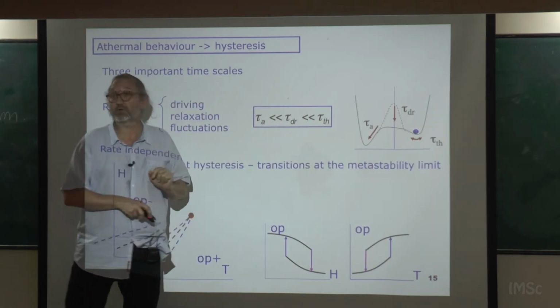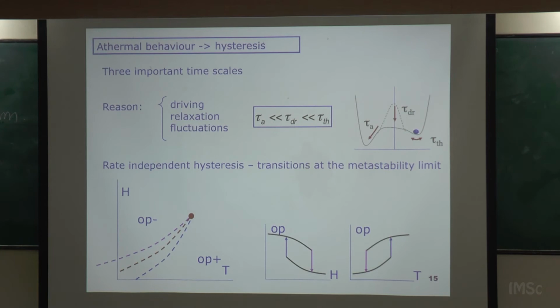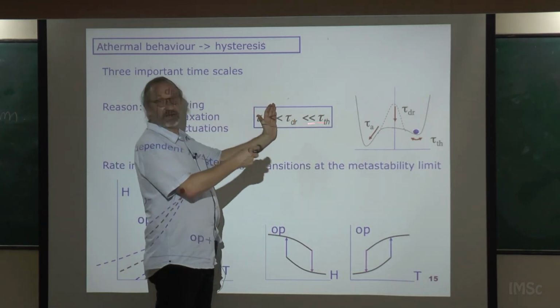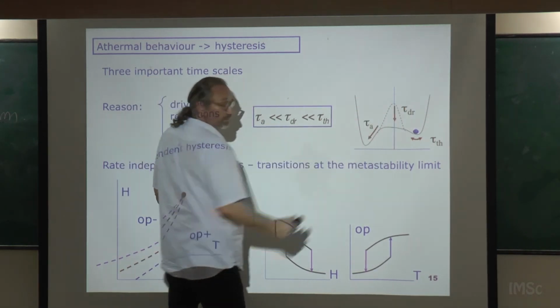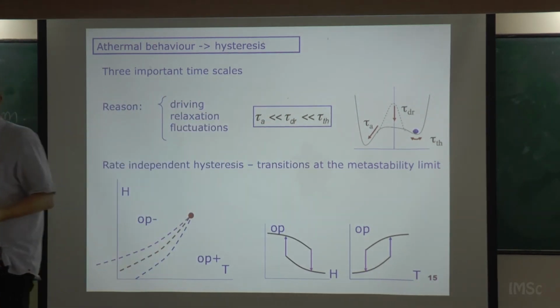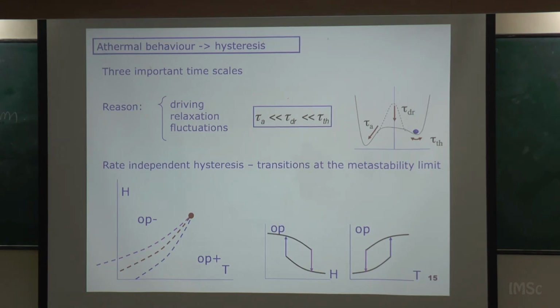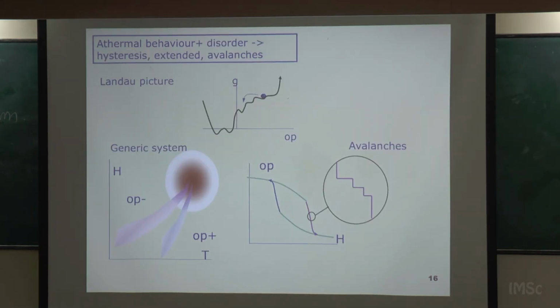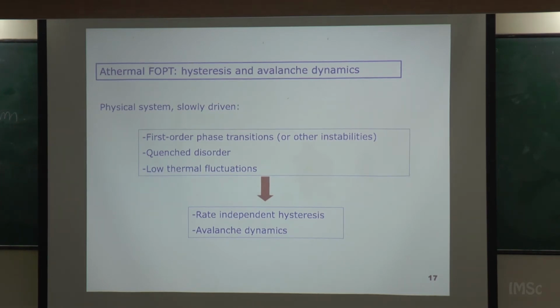It's only when you approach here or there that you will start to deform the hysteresis loop. So this is not the typical hysteresis loop that you get when you go too fast, where the system has no time. In that case, it's just a matter of these two times, one against the other. But I'm saying that these two values are very far separated, so I can move in between, and then I have rate-independent hysteresis. This is the message. So that's an indication that you can be in this scenario: rate-independent hysteresis, and then avalanche dynamics. So this is the framework that allows us to describe this problem.